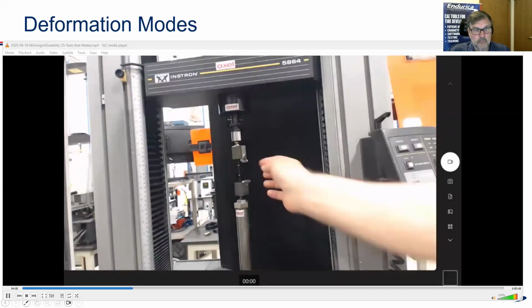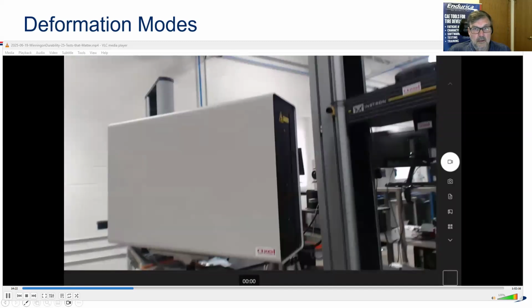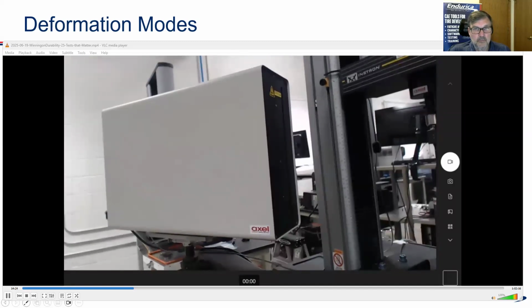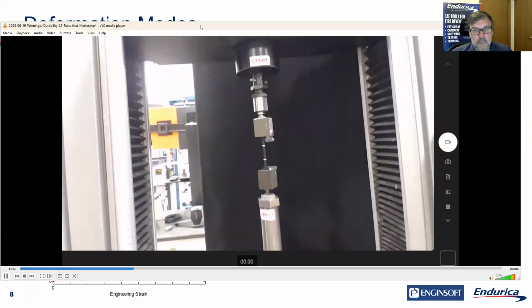Garden variety tensile tester: it's a crosshead, load cell, and a specimen. And you'll notice there's two stickers on the specimen. In this case, we're using a big laser. So this is a laser extensometer to measure the strain on the specimen. It's absolutely critical that we measure strain with a non-contacting device. That's very old world to be grabbing specimens. It's not okay to assume that the crosshead travel is correct. So we have to do this. I'm not going to say any more about that. That's kind of old news.